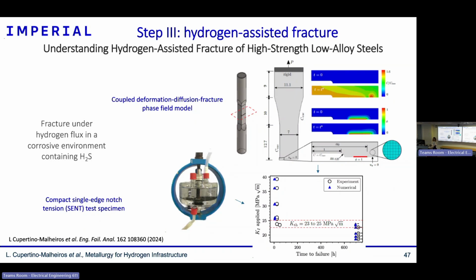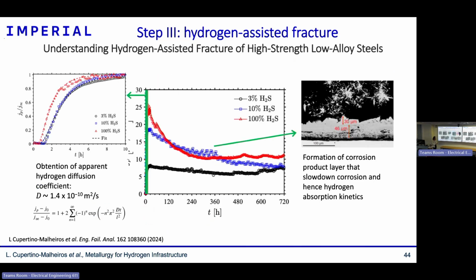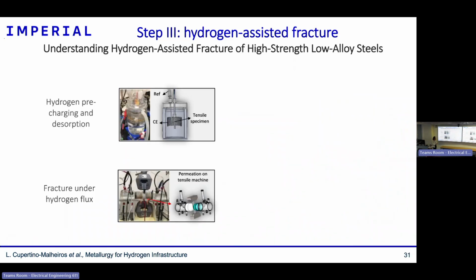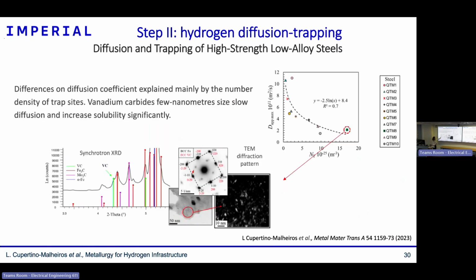Well, someone's asked, is it only vanadium carbides that reduce susceptibility towards hydrogen embrittlement? Yeah, one thing I need to point out here that could be misleading. The vanadium carbides here did reduce the kinetics of hydrogen diffusion. I didn't say it reduced hydrogen embrittlement susceptibility. And in that case, when you test those steels in situ with hydrogen entering, you could saturate these traps. This didn't result in a better hydrogen embrittlement susceptibility. So this is the first point I want to say.